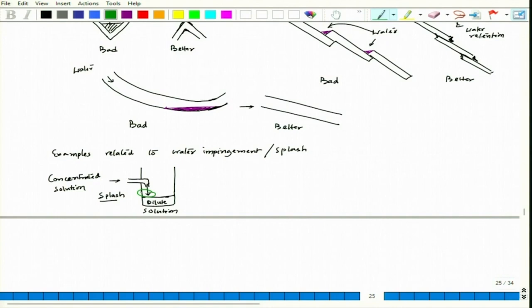Fine. So this particular wall can have corrosion. We can say there could be a possibility of severe wet and dry kind of corrosion, and as the concentrated solution is sticking to the surface, it can lead to a higher degree of corrosion there. So, in fact, we have to avoid this splash. One way to avoid this splash is to reduce the gap between the exit point in the pipeline system through which the concentrated solution is coming out and the top layer of the dilute solution. So, that gap should be reduced. This gap we have to reduce. The gap should be reduced to avoid splash. Now, this is poor, and the better design could be, so this is my tank where I am holding dilute solution.